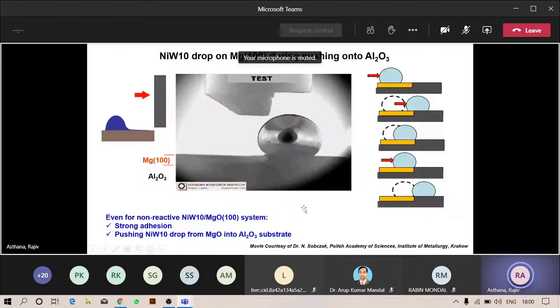The surface is no longer flat, it is curving because of the reaction. And the reaction product has a larger volume compared to the initial substrate, and that's why you are seeing the expansion of the substrate because of the actual reaction.